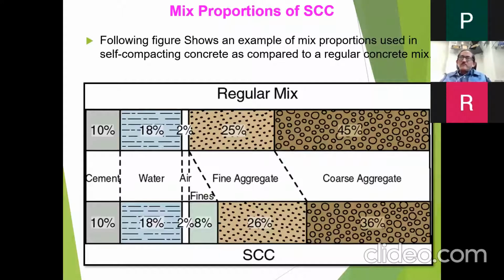Example of mix proportion used in self-compacting versus a regular vibrated concrete. Cement would be the same, say 10%, water would be 18%, the air would be 2%, but the fine aggregate would be increased from 25% to say 26% plus an additional 8%, which has been carved out from the coarse aggregate. So coarse aggregate percentage would go from 45% to 35% or 36%. So this is where there is a change in the composition of normally vibrated concrete and self-compacting concrete.